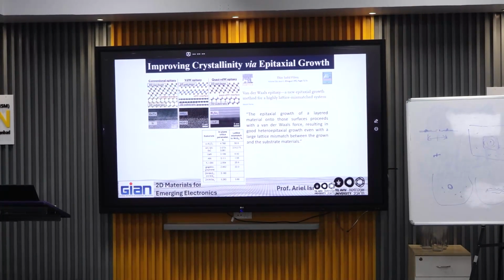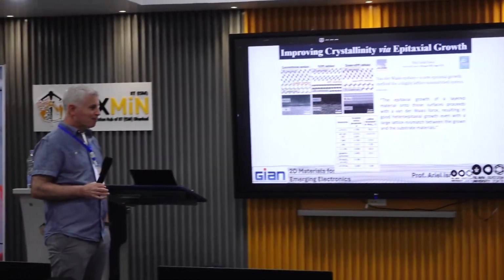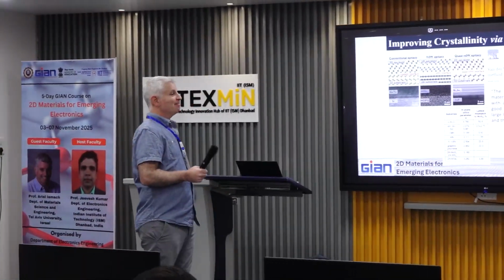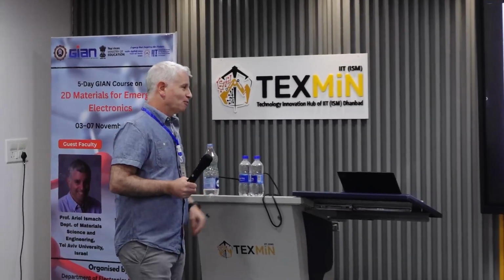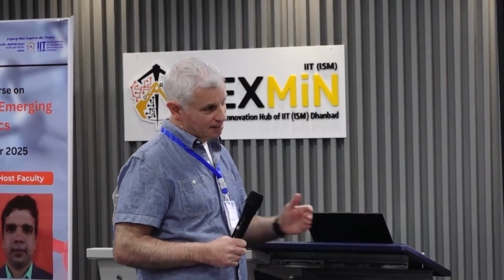So we did that. That's why I'm saying that I'm pretty confident. We didn't publish yet, but we did that. We did the low temperature epitaxial growth by doing that on CVD grown material. And when we compared with exfoliated, we didn't get any growth. So there are indications that it is true, but it still needs more.